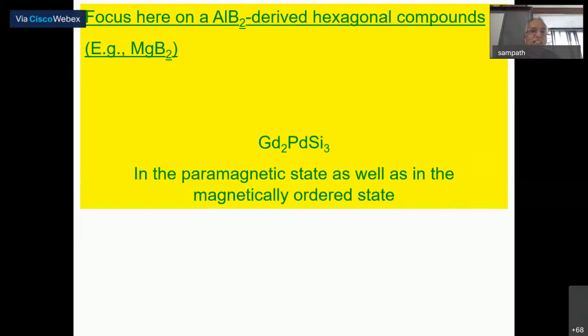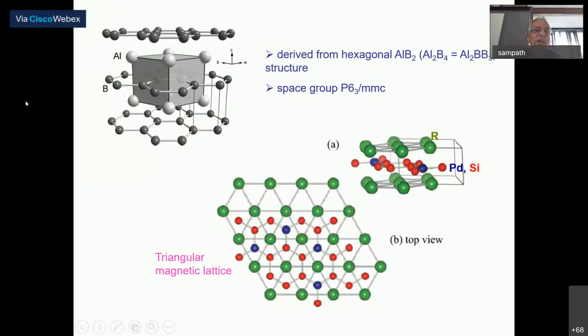And I show you the crystal structure here. This crystal structure contains the boron layer, then you have the aluminum layer, and then the bottom aluminum layer. Therefore, all the layers are alternating here. So in this kind of crystal structure, if you replace boron on the opposite side, in the hexagon here, you can actually replace it in an ordered manner. Therefore, you end up with two sites for rare earth instead of only one site. And we have plenty of compounds known in this structure. Unfortunately, this family was not studied. You can create ternary compounds out of a binary material.